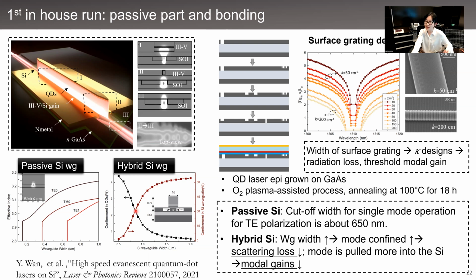And at the same time, the mode is pushed more into the silicon region, which results in a reduced mode overlap with the quantum dot region. So considering both these effects, a trade-off must be made to achieve sufficiently high modal gain for low threshold laser operation, as well as to maintain low scattering loss. And the hybrid silicon waveguide width was kept at one micron.